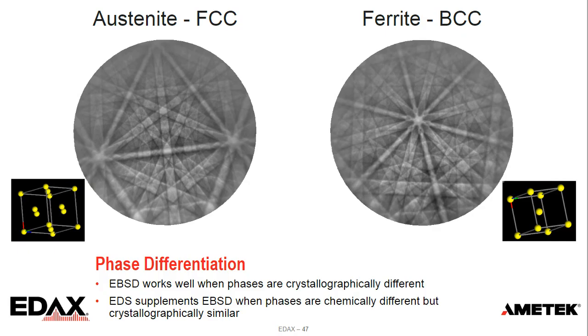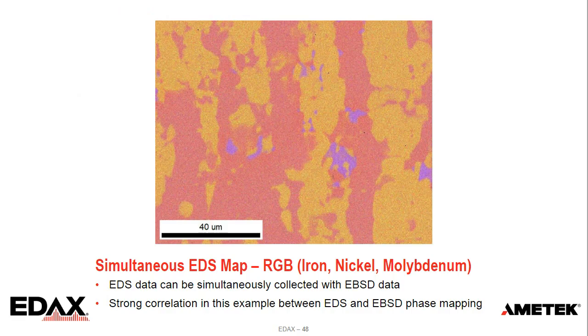And you can just see for this example, this is the 2205, and I've created just a single EDS map where it's RGB colored. So red is iron, green is nickel, blue is molybdenum, and you can see where the sigma phase is by highlighting where the moly is higher. And we see a strong correlation. If we look at the phase maps next to each other, they correlate well. And so it's very easy to collect simultaneous EDS, EBSD data now in a modern EBSD system. Both the EBSD and EDS detectors and the SEM chambers are all designed with that in mind.